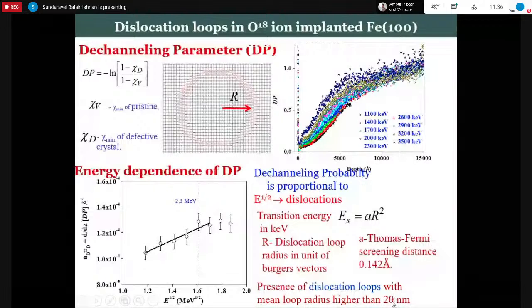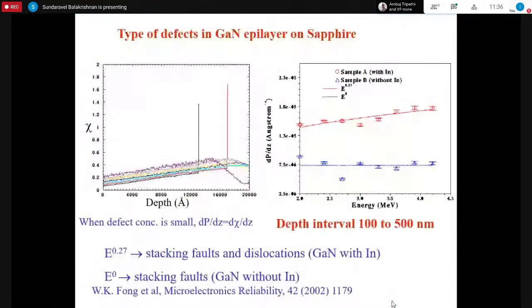And in the case of gallium nitride, we have seen this defect dependence. When we grow the sample of gallium nitride with indium, we get something like E power 0.27 or so. It means that there are dislocations as well as stacking faults, while when the sample is grown without indium, there are only stacking faults. So there is no energy dependence.